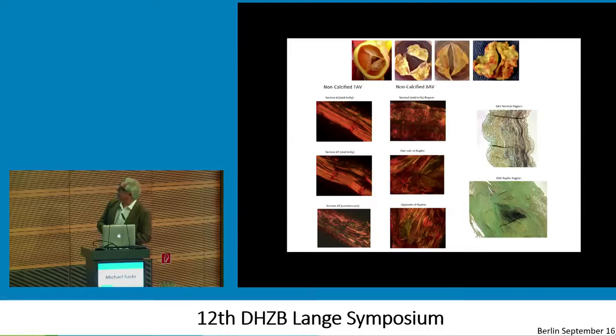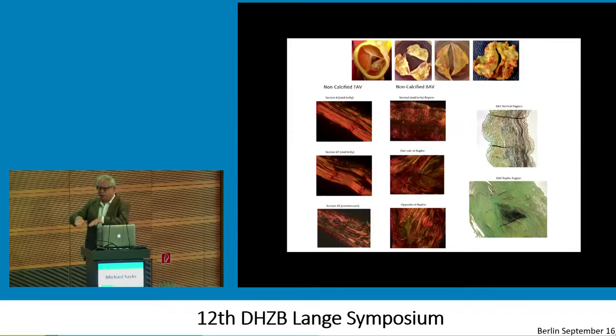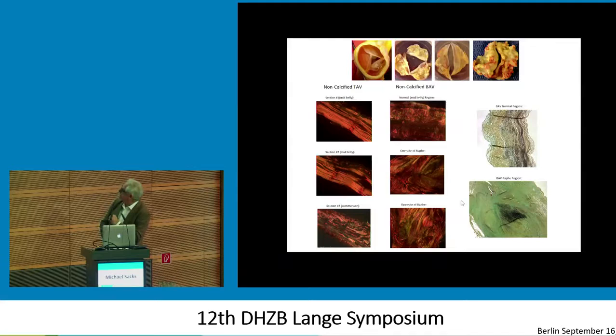The bicuspid valve is a really interesting anomaly. We did some architectural studies a couple of years ago from human explants. The normal valve, using Picrosirius Red, is extremely well structured. The bicuspid valve, on the other hand, can be very anomalous. I want to draw your attention to the anomalies not at the fiber level but at the layer level — I use the analogy of a layered cake where you take a spoon and mix up the layers before baking. What's happening is that the layers get mixed up. You can see a large chunk of elastin fibers that really should be in the ventricularis, stuck up in the fibrosa in the raphé region. So this anomaly is quite peculiar — it's not a random disarray of fibers, but a more organized anomaly.